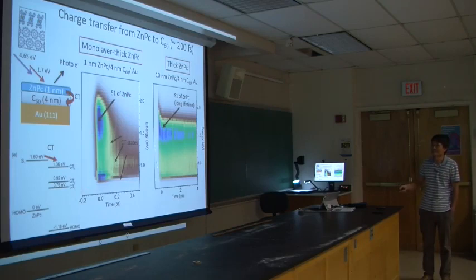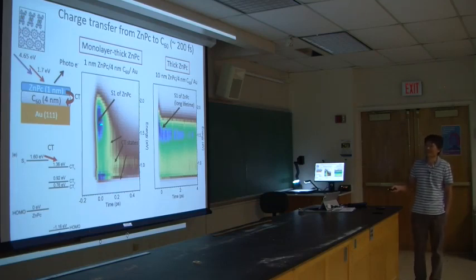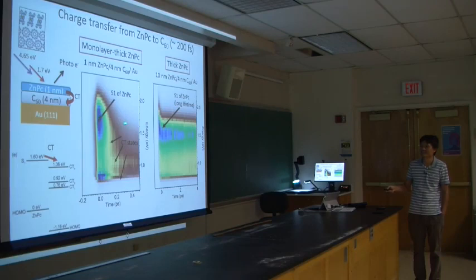Here is the photoemission spectrum that we collected at different delay times. Time is here, energy is here. You can see that initially we excite this so-called singlet exciton in ZnPc, which has the highest energy. The color is the intensity, by the way. This intensity decays really quickly, in about hundreds of femtoseconds. What happens is that it decays, and then you see these other states get populated. So the singlet state transfers the electron to C60 to produce these different CT states.